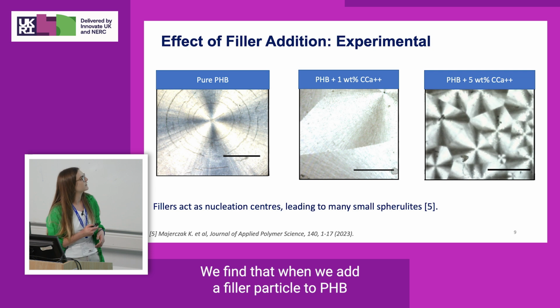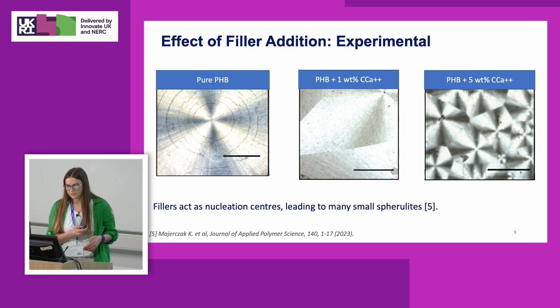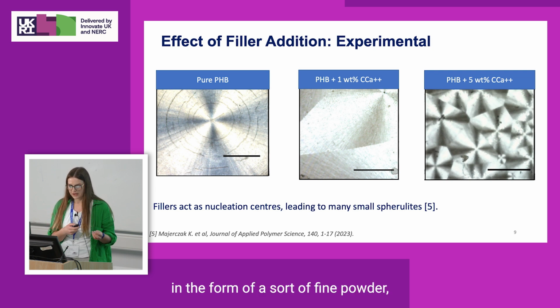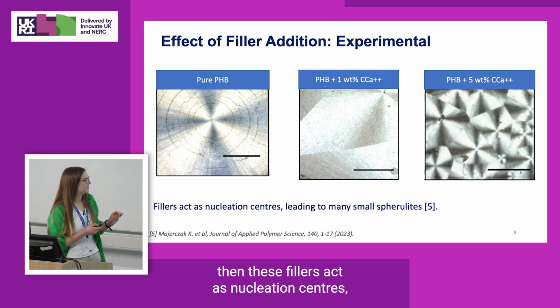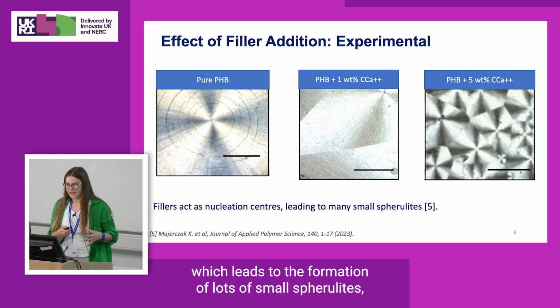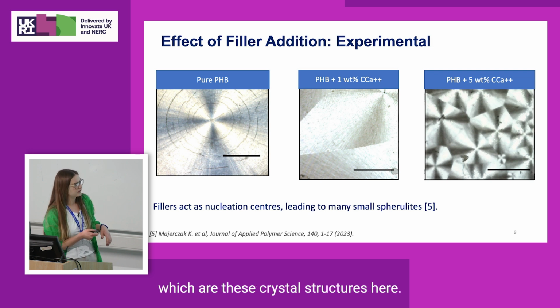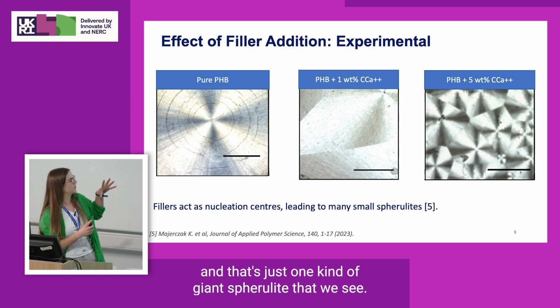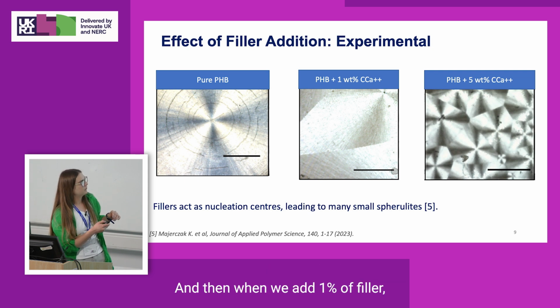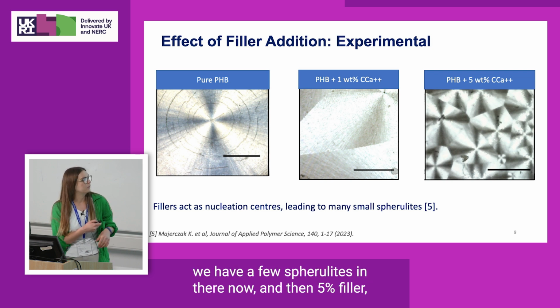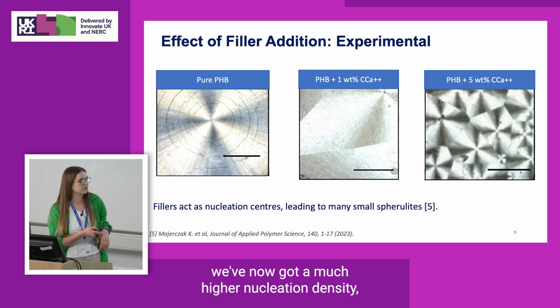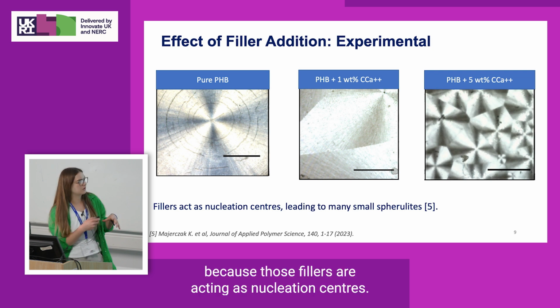We find that when we add a filler particle to PHB in the form of a fine powder, then these fillers act as nucleation centers, which leads to the formation of lots of small spherulites, which are these crystal structures here. So this one on the left, that's pure PHB, and that's just one giant spherulite that we see. And then when we add 1% of filler, we have a few spherulites in there now, and then at 5% filler, we've now got a much higher nucleation density because those fillers are acting as nucleation centers.